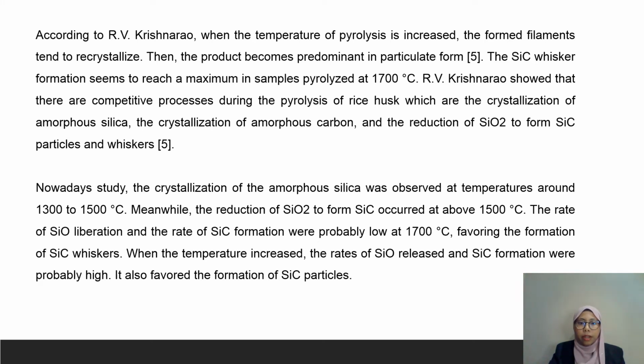R.V. Krishna Rao showed that there are competitive processes during the pyrolysis of rice husk, which are the crystallization of amorphous silica, the crystallization of amorphous carbon, and the reduction of SiO2 to form SiC particles and whiskers. In the present study, the crystallization of the amorphous silica was observed at temperatures around 1300 to 1500 degrees Celsius. Meanwhile, the reduction of SiO2 to form SiC occurred above 1500 degrees Celsius. The rate of SiO liberation and the rate of SiC formation were probably low at 1700 degrees Celsius, favoring the formation of SiC whiskers. When the temperature increased, the rates of SiO release and SiC formation were probably high. It also favored the formation of SiC particles.